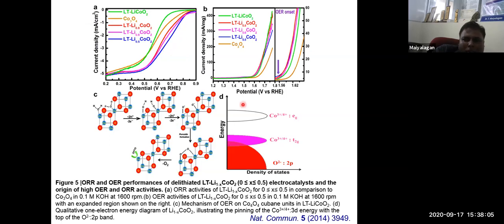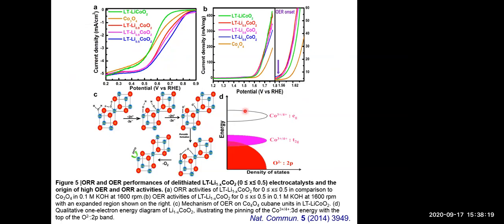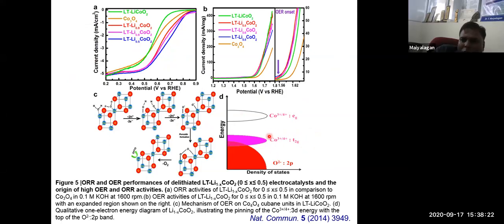To improve the performance, we tried to delithiate. We remove the lithium from this low temperature lithium cobalt oxide, to 0.8, 0.6. When I remove lithium, the oxygen reduction peak shifts. The Co3+/4+ t2g band overlaps with the oxide band. You can see the density of states in the oxide bands. For oxygen reduction and oxygen evolution, this oxygen 2p band is very critical. When you delithiate and overlap the oxygen 2p band and the Co3+/4+ band, the oxygen evolution and reduction reactions are better.